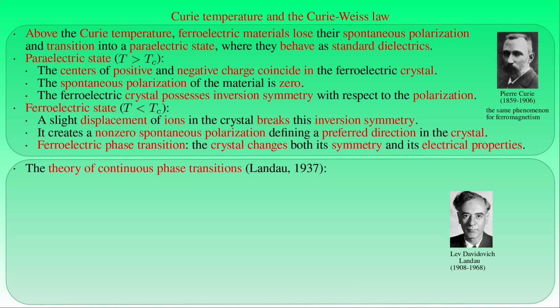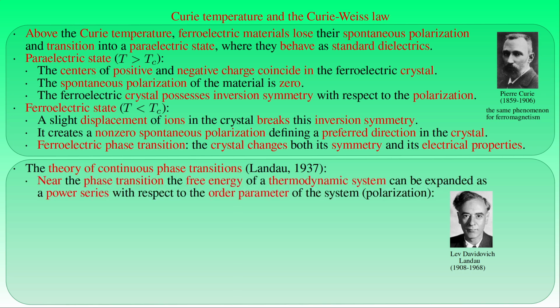Because a thermodynamic system at constant temperature and volume reaches equilibrium by minimizing its free energy, Landau assumed that near the phase transition the free energy can be expanded as a power series with respect to a quantity called the order parameter of the system. In the case of ferroelectric materials, the order parameter of the phase transition is the polarization P, for which the free energy is an even function of the small values of the polarization near the critical temperature of the phase transition. That is, the free energy F evaluated at the polarization P is equal to F evaluated at negative P.